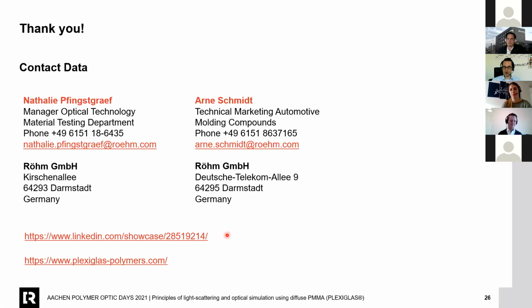And for sure, plastics can be destroyed by super high heat or high shear rates, and they can show distortion. So they are getting soft, rubber-like during the injection molding. And if you freeze the part very fast, you can get anisotropic scattering properties. So this can happen. One thing to avoid it is we are using for our simulation parameters the experimental approach to consider depolymerization effects of the material, and for sure distortion effects.